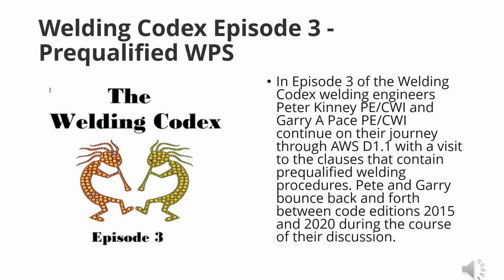The other thing I wanted to point out, in one of the differences between Group 1 and Group 2, you may see the same materials in both, but what you will see is in Group 2, they become thicker. And that happens a little bit in Group 3, but not nearly as much as it is from Group 1 and 2. And the reason for the change in thickness is the thicker you make a material, normally the more, I'll say, trash that you'll start to get, especially center line of the material. It won't be as clean. The base material indications will become larger, and one of the big ones is manganese sulfide stringers. You'll see a lot of those in thick material.